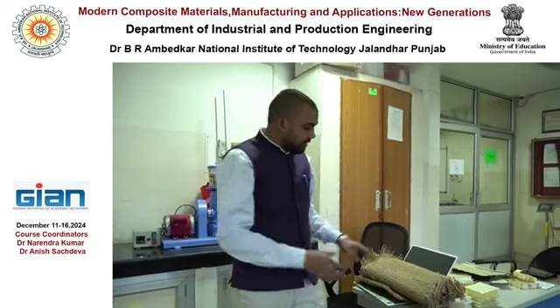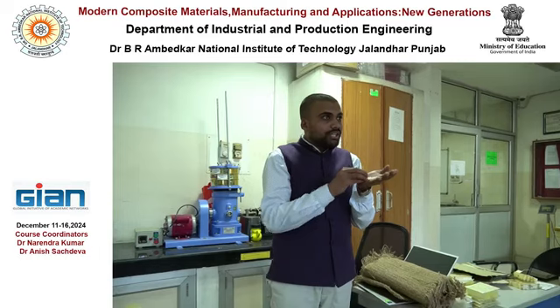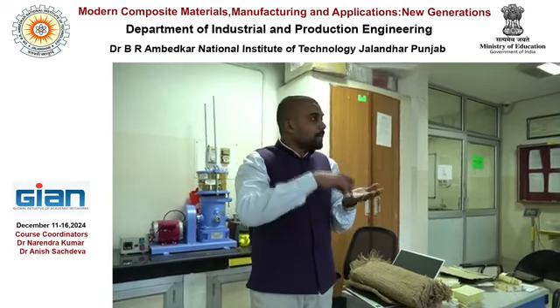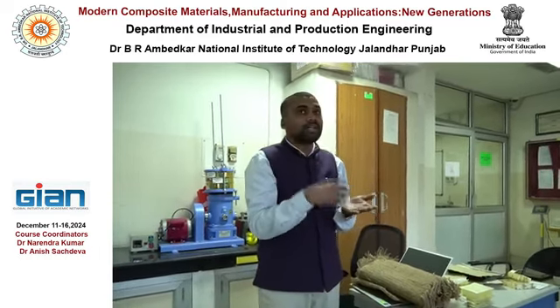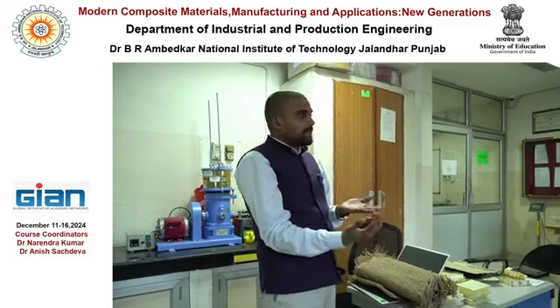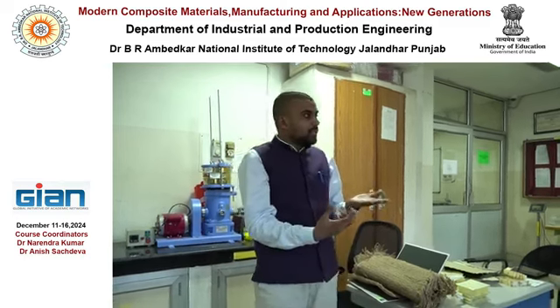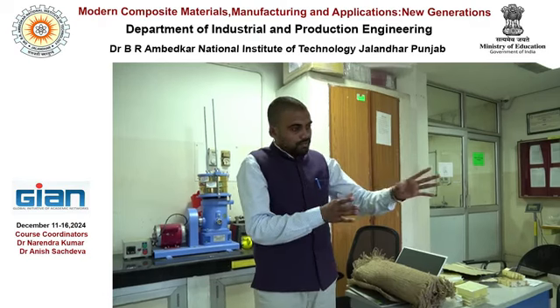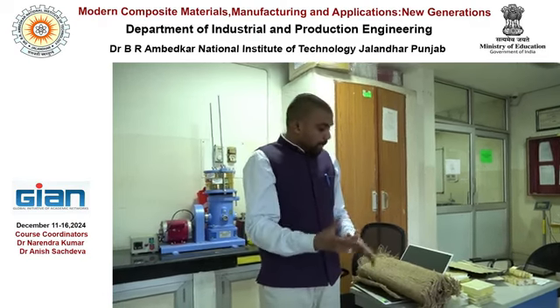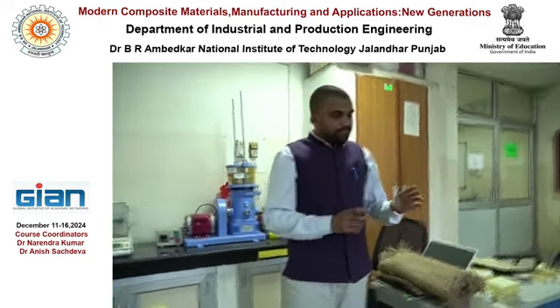we have already done one study showing that when you change the number of binders, the impact energy absorption of the composite material changes. Right? The more binders, the more the impact energy absorption. And one more thing is that